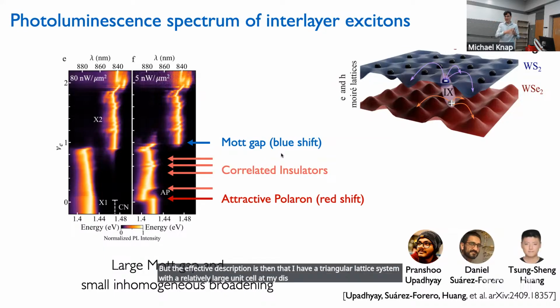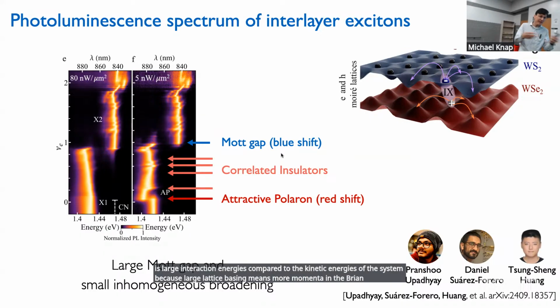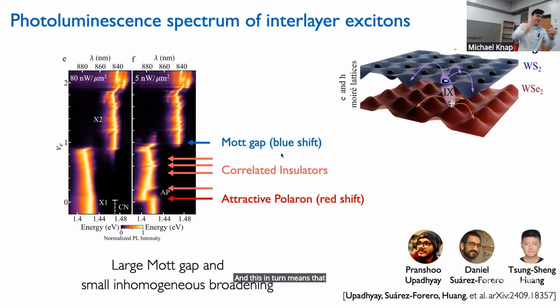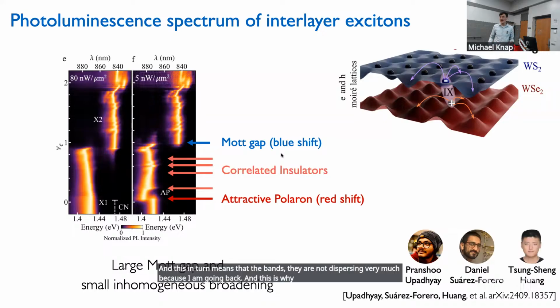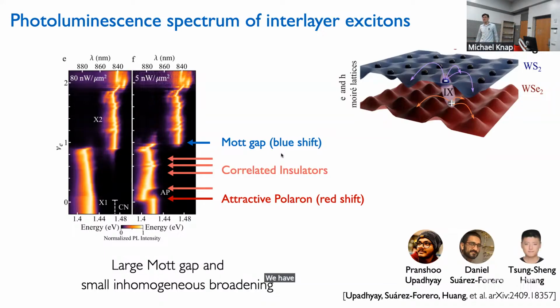So that's where the Moiré physics is coming from. As a consequence of this large unit cell, we have large interaction energies compared to the kinetic energies of the system, because large lattice spacing means small momenta in the Brillouin zone, so there's a lot of backfolding going on, and this in turn means that the bands are not dispersing very much. This is why in these kinds of settings, we have the opportunity to observe many strongly interacting states of matter, and they have been observed.